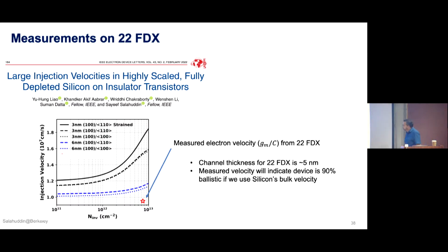So we wanted to go back there. A few years ago, we measured a 22 FDX technology from GlobalFoundries, directly measuring the transconductance over capacitance. Remember, the transconductance is capacitance times velocity. We could get a velocity that is very close to 1e7. Now, this 22 FDX has around 5 nanometer thickness, it's quite thin. If you believed that nothing changed in the silicon band structure, you would say that this device is working at 90% of the highest velocity, the ballistic velocity of a bulk silicon transistor, which makes no sense. Because there are many other measurements you can do to show that this device is actually at 50% of the highest velocity that you can achieve.